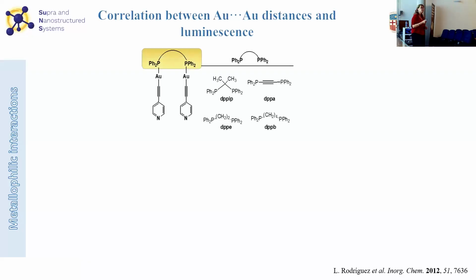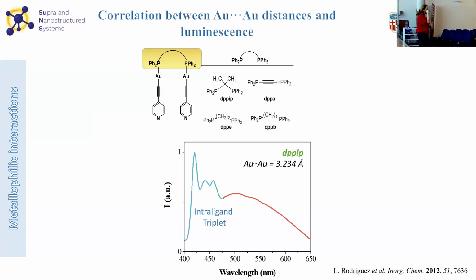As I am also working on photophysics, we have seen that the presence of these metallophilic interactions plays a key role in the resulting luminescent properties. So some years ago, we made a systematic study in which we made several compounds that are dinuclear since they contain two gold centers, exactly with the same chromophore, this pyridyl ethynyl ligand, and these two gold centers are coordinated by a diphosphane. This diphosphane differed in flexibility and rigidity and also in chain length. With all of them, we could grow single crystals, so we could measure the distance between the gold metal centers.